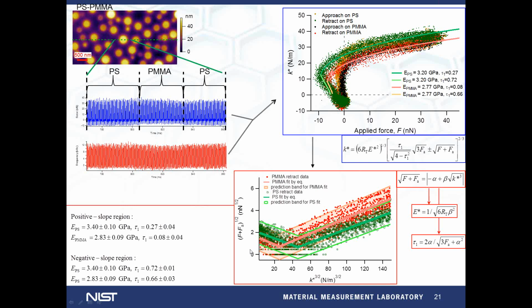And interestingly, the transition parameter shows bigger values for the unstable region, and these large values are connected with the contact breaking events and indicate the predominant contribution of the short-range adhesive forces inside the contact. So this indicates that for contact breaking, we have a larger contribution to the work of adhesion from the short-range adhesive forces compared with that from the long-range adhesive forces.